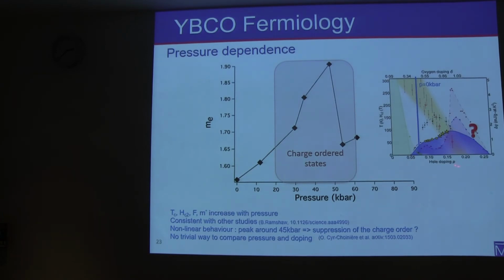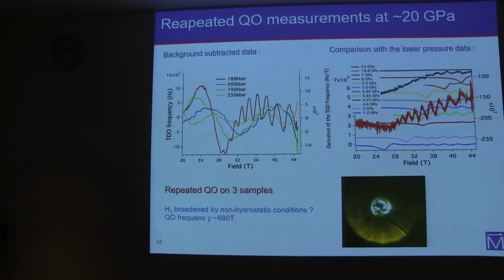Our main focus was to apply some pressure and see if we could get to that region of the phase diagram, so to the high pressure overdoped side. And this is what we did repeatedly, on pressure cells at 20 GPa and beyond.